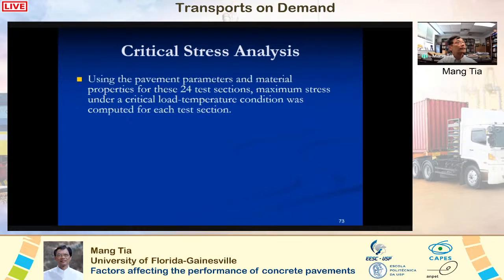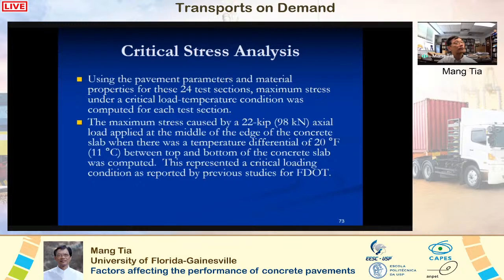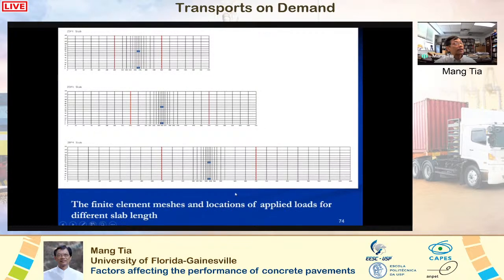Okay, in the critical stress analysis, using the pavement parameters and material properties for these 24 test sections, maximum stress under critical load-temperature condition was computed for each test section. The maximum stress caused by a 22 kip axle load applied at the middle of the edge of the concrete slab, when there was a temperature differential of 20 degrees F between the top and the bottom of the concrete slab, was computed. This represented a critical loading condition as reported by previous studies for Florida DOT. And the FECONS computer program was used for the stress analysis.